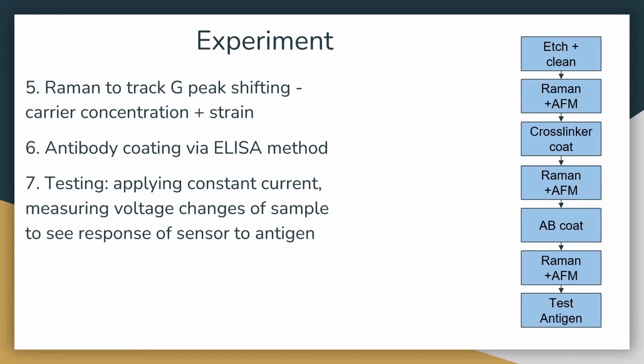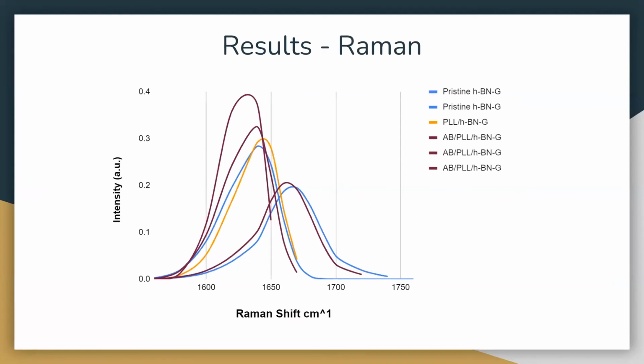Next, I conducted Raman spectroscopy again to track the shifting of the G peak, which is actually related to the graphene's carrier concentration and strain. The graphene's G peak is essentially the in-plane vibrational mode, or the stretching mode, of the graphene. Then I coated each sample with an antibody coating using the ELISA method, and then tested each sample by applying a constant current and then measuring the voltage change of the sample to see the response of the sensor to the COVID-19 antigen.